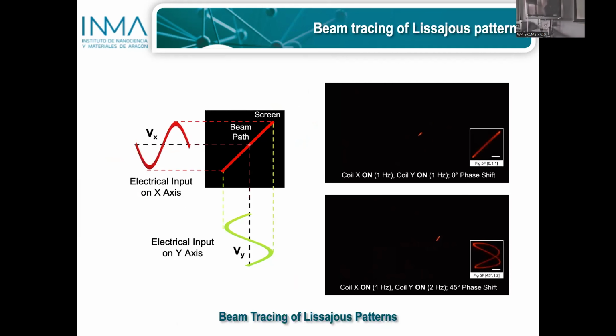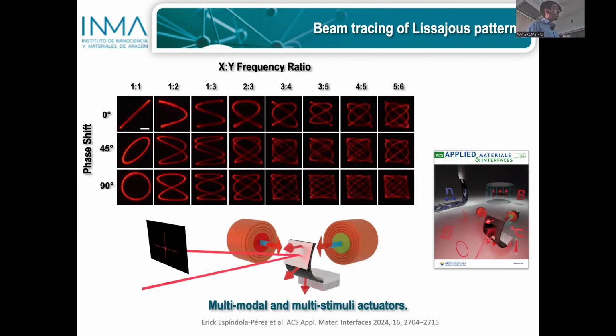We can combine both coils and apply a couple of sinusoidal signals, and if they are in phase, then we get this linear movement. But if we now start to play with the frequencies, we can generate a variety of Lissajous figures, demonstrating the capabilities of these multimodal, multi-stimuli actuators.